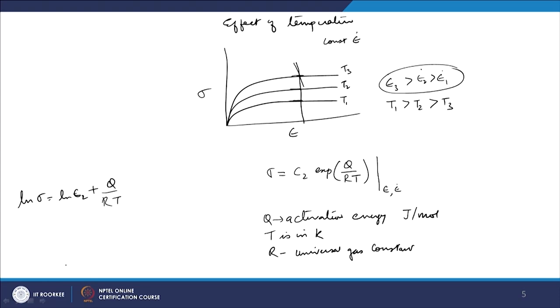So, if I plot a curve between ln of sigma versus 1 by T, then 1 by T is increasing here, meaning temperature is decreasing here. So, you can see my flow stress has to increase here. Different values come from here. I can fit a best fit straight line, and the slope will give me the value of Q by R. So, from here I can find out the activation energy for deformation. As we saw, when relating stress with strain rate, the important parameter is the strain rate sensitivity index. When relating temperature with stress, the important parameter is the activation energy of deformation.